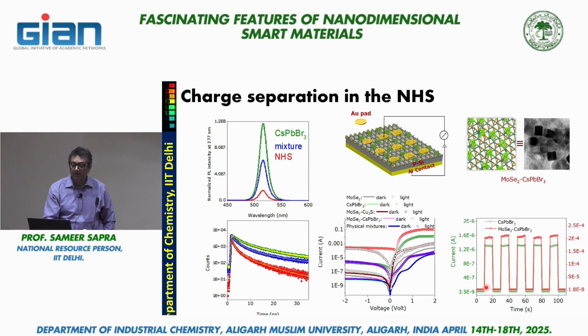as I said, these are very well stuck onto the molybdenum selenide. If you look at the fluorescence of cesium lead bromide, these are very fluorescent particles. They look like beautiful green particles. You make the nano heterostructure, the fluorescence gets quenched because immediately the electron and hole, because of that type 2 kind of heterostructure, get separated and they cannot recombine. And if you just use a mixture without the 4-ATP, then because of collisional quenching, some of the fluorescence is lost, but not to that extent.